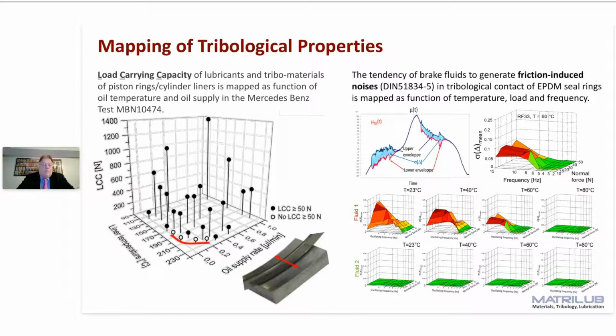The first point is, as you see, the test specimens are machined from real parts. This has the advantage that all unknown parameters which exist are in these parts, because these are production parts. When you produce a test specimen aside, they are in any case different from those from production parts: surface topography, residual stresses, many things. And in this test here, you have this critical load carrying capacity for a piston ring cylinder liner as a function of the liner temperature, as a function of the load supply. And you must be sure that the test results are under all conditions above 50 newtons, to make really sure that under all operating conditions, this couple, including the lubricants, will not scuff.